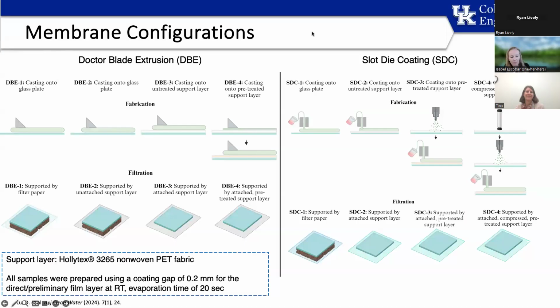And so the purpose of the work, and we published this last year in the Nature Portfolio Journal Clean Water, what we did was make a full comparison of Doctor Blade and slot die coating, and we made the membranes both on a glass support, and then we just put them on top of a support paper for filtration. We also put them on top of the PET non-woven support, the Holitex, for filtration. Then we started casting directly on the support, or in here where we would make a very thin layer of dope on that support and then cast the full membrane on